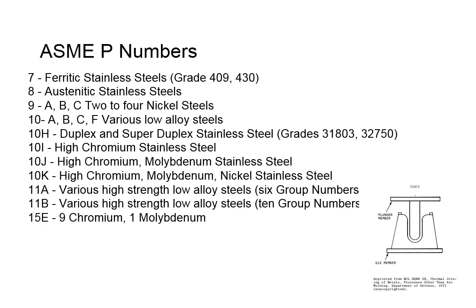So if you see anything that's like 9 chromium, 1 molybdenum, that's a big warning flag. You're on thin ice there. You need to do some reading if you ever have to qualify a weld procedure with that type of material, because you're definitely swimming in the deep end of the pool, and not only are there sharks, but there's piranhas in that pool with you. So you've got to know what you're doing if you're going to weld the 15Es. Not a very forgiving group of materials, but something to keep in mind.